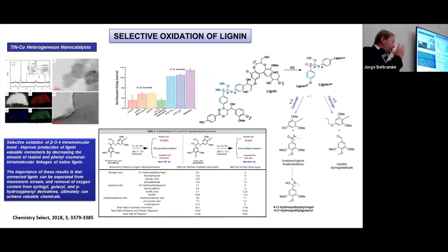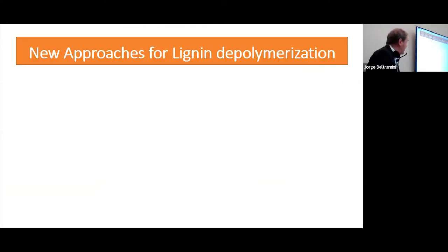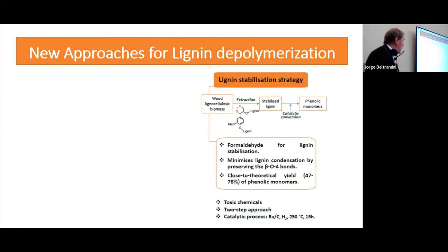So with this principle, we then said, all right, what is in the literature and what is in the industry? We know very well the lignin stabilization strategy that I mentioned the other day. This is a two-step strategy. You separate the lignin, but you sacrifice the carbohydrate fraction. The carbohydrate fraction will be destroyed. The problem is that you use formaldehyde as a solvent, which is a very risky chemical, and we need to work with a two-step approach. We need to inject hydrogen, which is very expensive, and we need to use catalysts based on ruthenium, which is a very expensive material also.